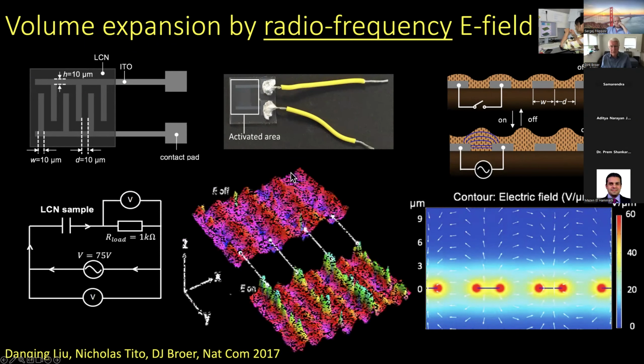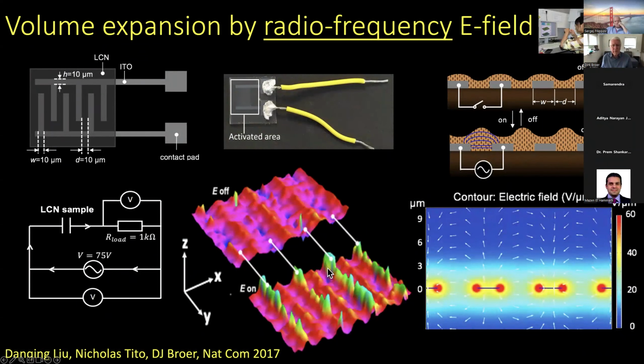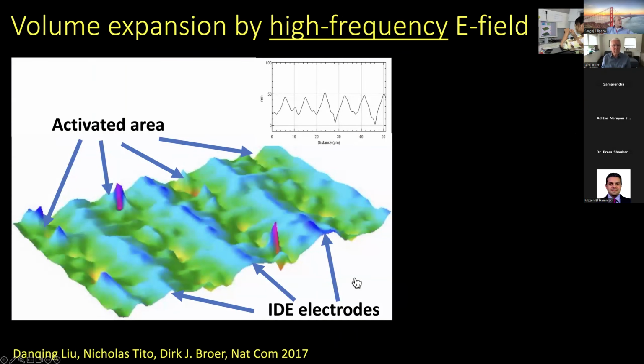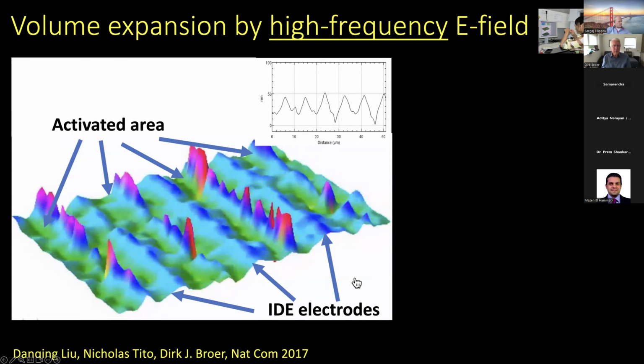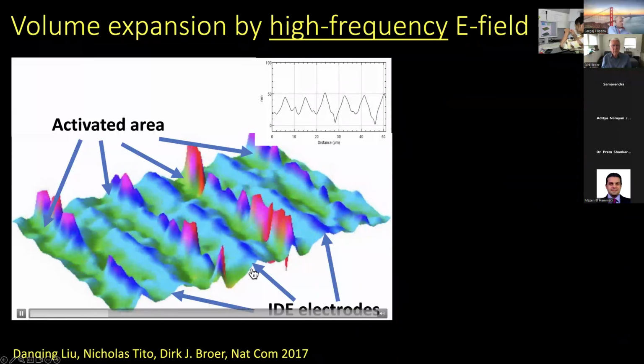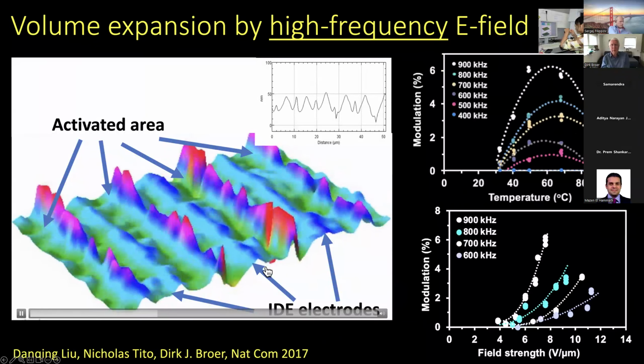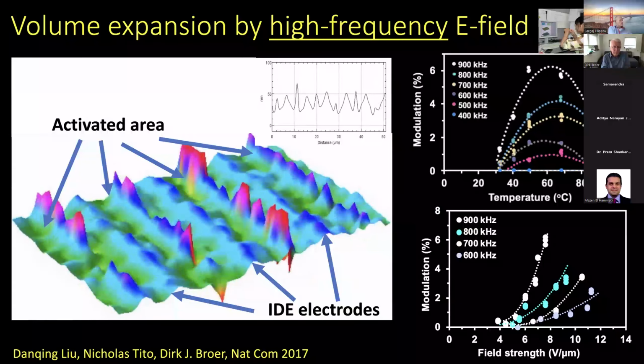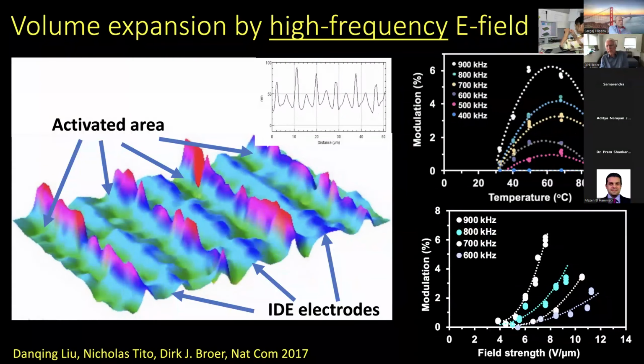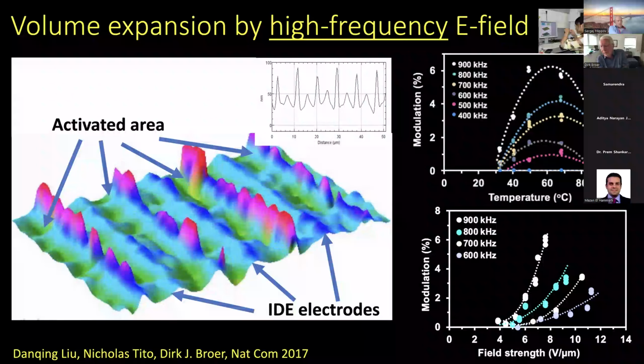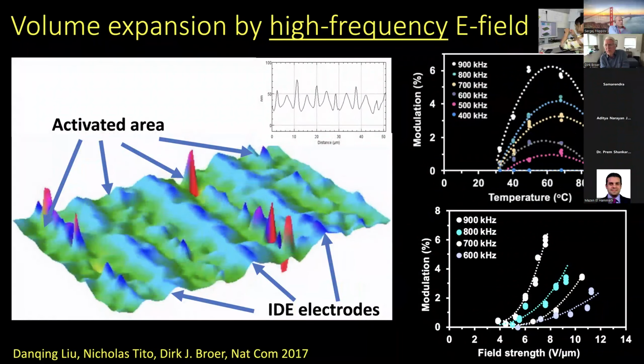And this is the interference measurement in the off state. Well, you see the pattern of the electrodes. In off state, the patterns of the electrodes are higher, and as soon as you start actuating, the structure starts to form. And this is the movie related to that. Again, this is the position of the electrodes, and upon actuation, we are forming this volume, this free volume, and the surface starts to expand.